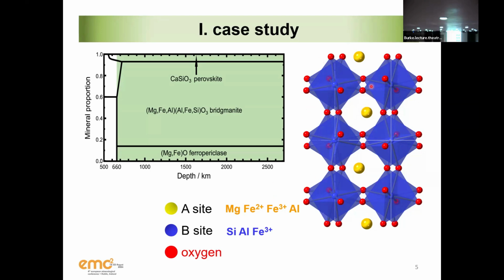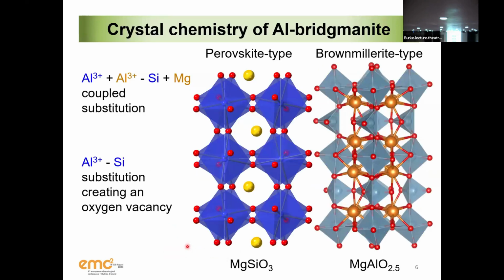We already heard about perovskite at the beginning of the week. What's happening is that, of course, in the Earth, these cations can be substituted. What we were interested in was a particular substitution, the one of aluminum. Because aluminum is a trivalent cation, you can have two different kinds of substitution mechanisms. One is the coupled substitution, where you have one aluminum going to the octahedral site in place of silicon, and one aluminum replacing magnesium at the big cavity.